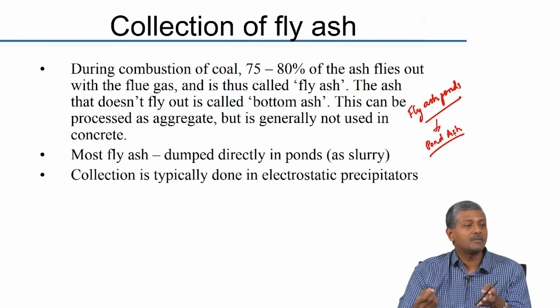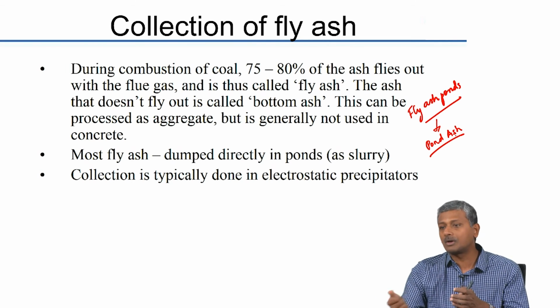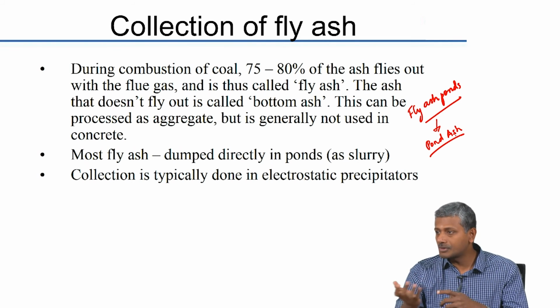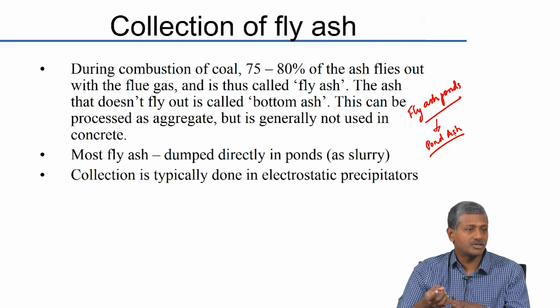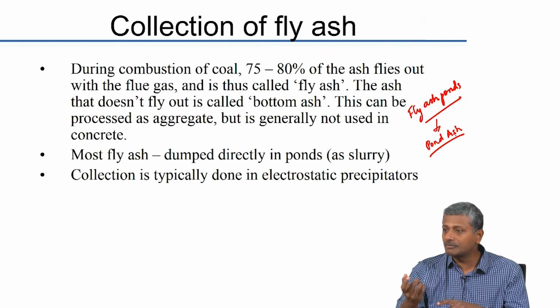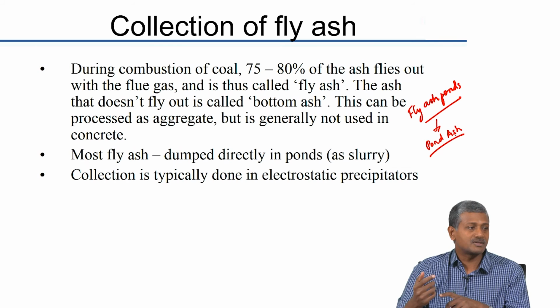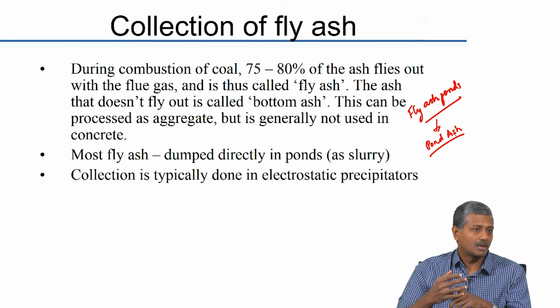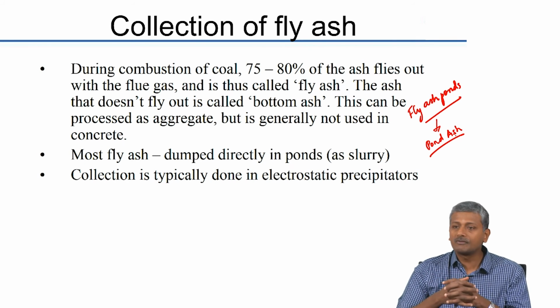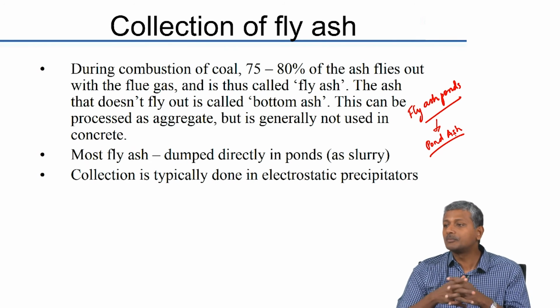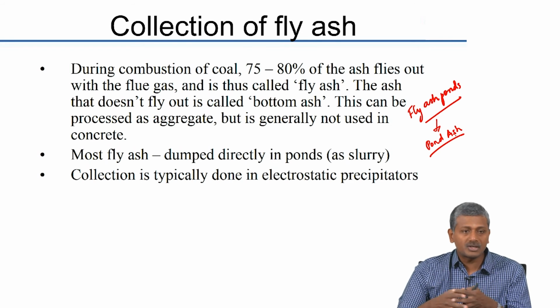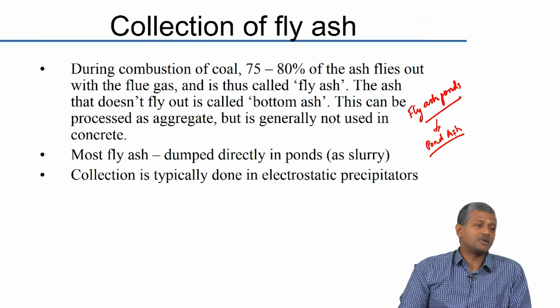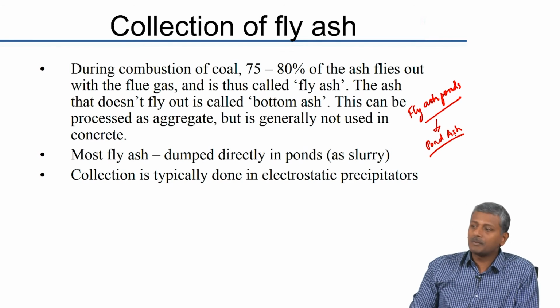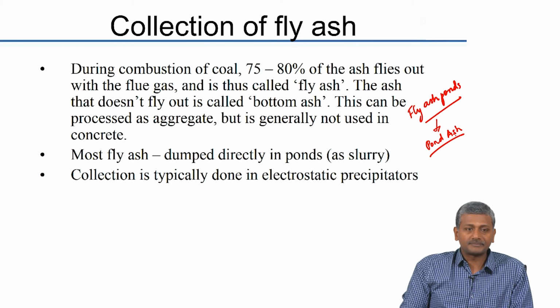Okay. Now, the issue is when you leave it in a pond, what may ultimately happen is that there may be some heavy metals present inside the fly ash, which may start seeping or leaching out into the groundwater, like arsenic for instance, that is often present in fly ash. And because of that, a lot of thermal power plants in the US had to be closed because of the dangers of arsenic pollution from the fly ash ponds. Okay. So, again there are a lot of issues with dumping of fly ash. So, because of that, in spite of the higher energy required to actually convert them into useful resource materials like aggregates, many people are still in favor of doing that.